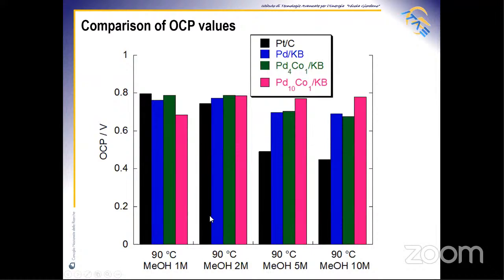The high methanol tolerance properties of palladium and palladium black is also demonstrated by these variations of open circuit potential values. In a direct methanol fuel cell, the open circuit potential is an important parameter to assess the methanol tolerance effect. The cell based on palladium and palladium cobalt alloys shows the higher open circuit potential than the reference cell, that shows a significant decrease as the methanol concentration increases. This result is a clear indication of the tolerance toward the methanol crossover of the palladium based catalyst.